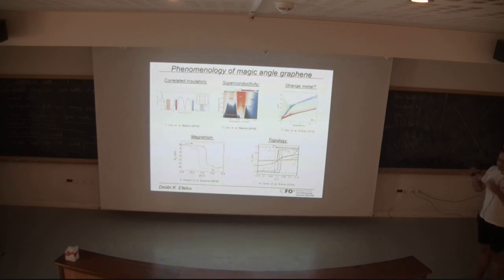Okay, so that is one of the advantages, and the other advantage, which I think is really exciting, and which has nothing to do with the unconventional superconductivity part, is that in the last year or so, a lot of other phases were discovered in twisted bilayer graphene. As I mentioned, we have the correlated insulators, we have the superconductors, then recently a strange metal phase was also reported in graphene. Then just a couple of weeks ago, another paper by the Stanford group was published, which observes magnetism in the very same compound, and topological states were also just reported a couple of weeks ago. So in principle, to me, even besides this unconventional superconductivity story, this system appears to be extremely rich, where a lot of different phases can be approached in a very tunable way, just by slightly twisting the layers one on top of another, or just by applying electric fields and gating the system from one phase to another.